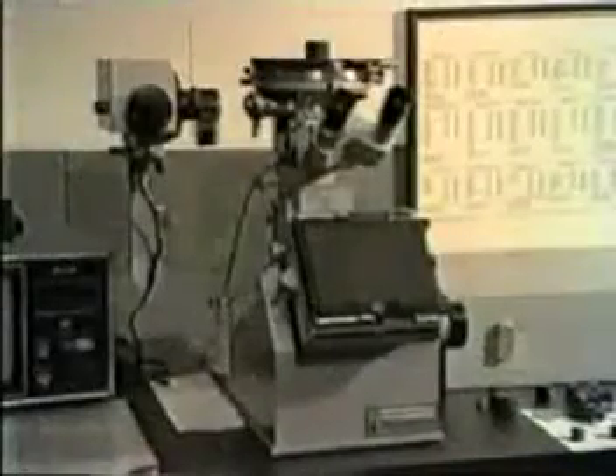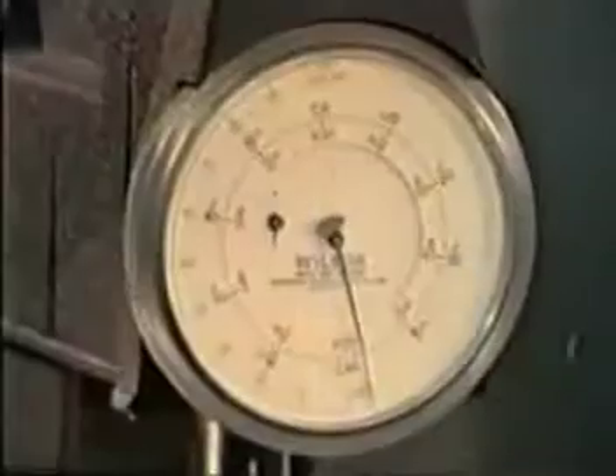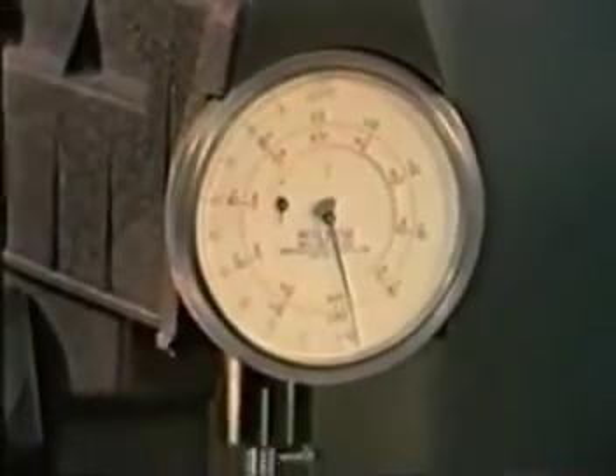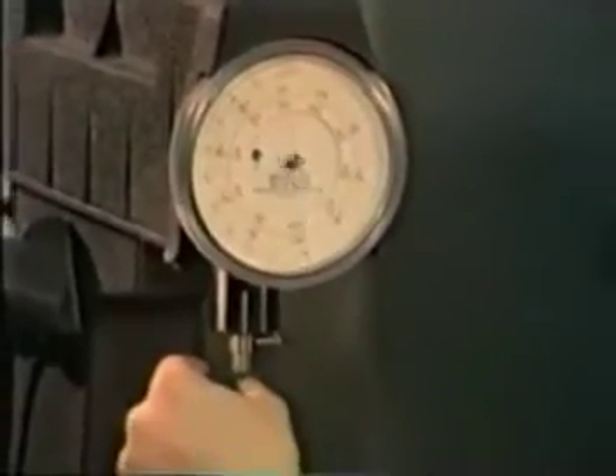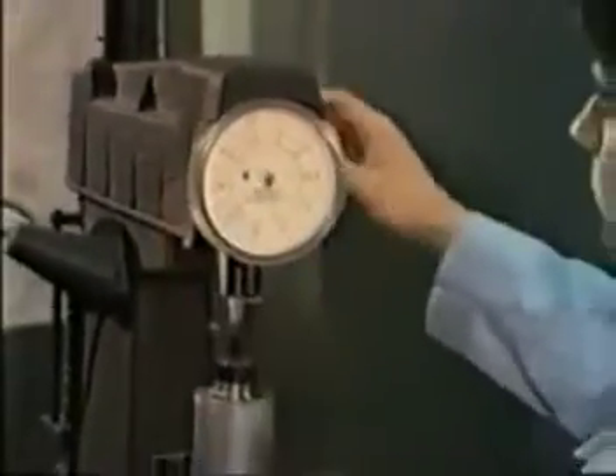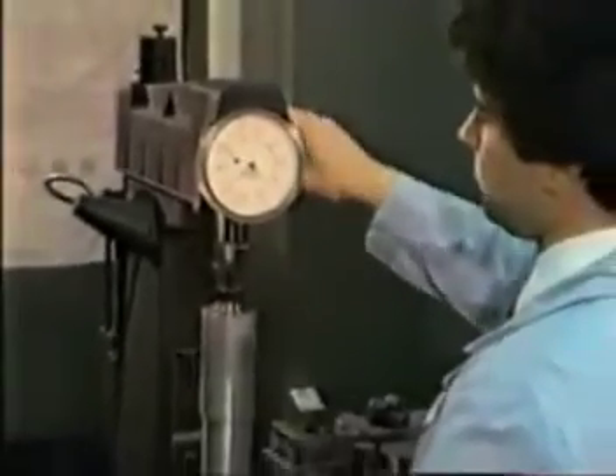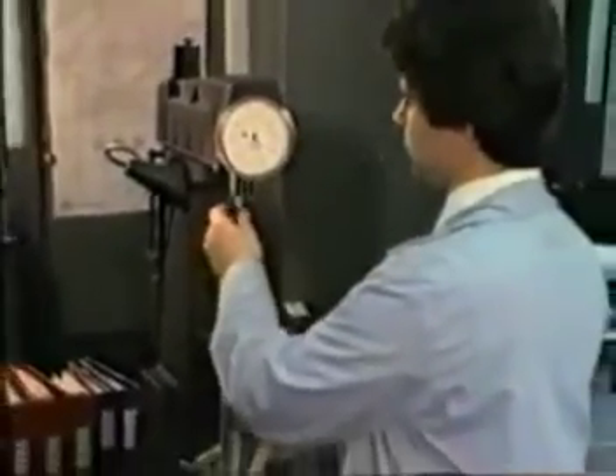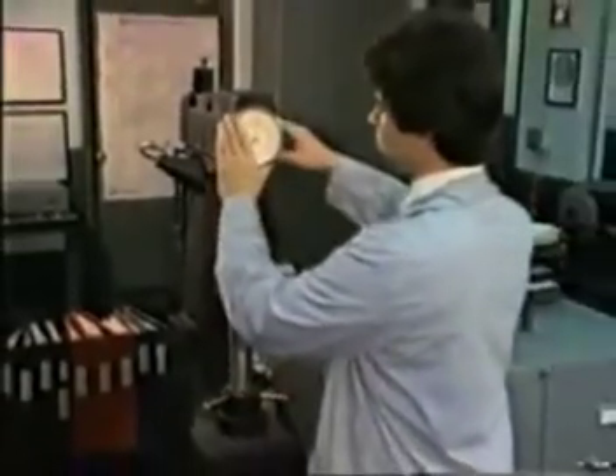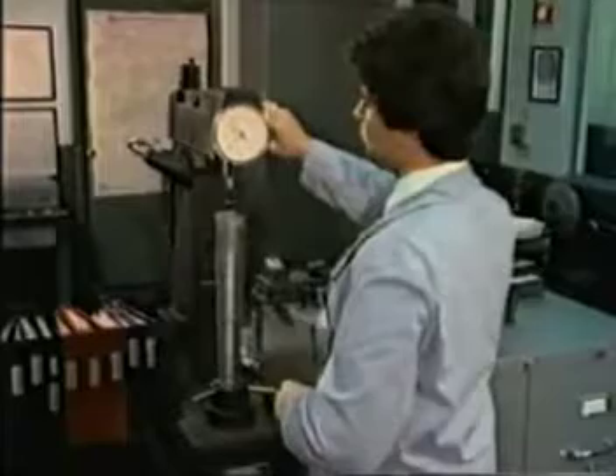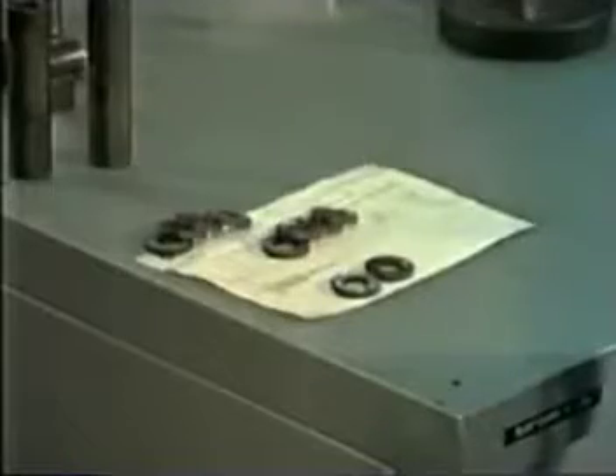Modern heat treaters use a variety of process control and inspection procedures to ensure that maximum quality is consistently maintained throughout heat treat processing. As part of this learning experience, we would like to explain a few of them. The Rockwell hardness tester is probably the most common piece of equipment in use today for inspecting the hardness of alloy steels. This instrument measures steel hardness by the depth of penetration of the diamond brale or steel ball under a fixed load condition. Preparation of the material surface before testing is of major importance.